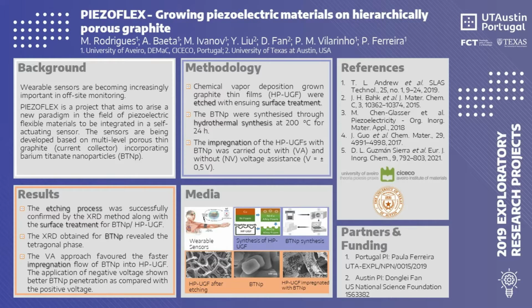The Austin Group, represented by Dr. Donglei Fan, grew flexible porous graphite thin films with different structures. The flexible thin films were synthesized with similar procedures, utilizing chemical vapor deposition graphite growth on nickel and copper templates. All templates were etched to eliminate the nickel layer and be left with the graphite templates. The etching solution contains hydrochloric acid and iron chloride, which immerse the templates for 24 hours or longer.